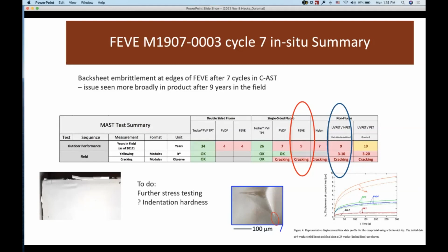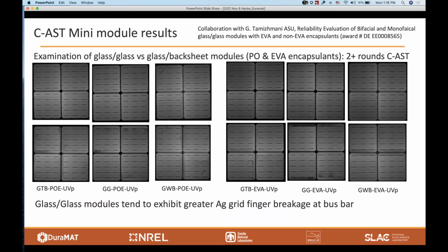So that's the results for the PET and the FEVE backsheet so far. And I'd like to move to the second of the two important results that I've got to show today. And that's the 2x3 matrix of polyolefin and ethylene vinyl acetate, EVA encapsulant with transparent backsheet, glass in the back, and white backsheet. So this is only after 2 rounds of combined accelerated stress testing.